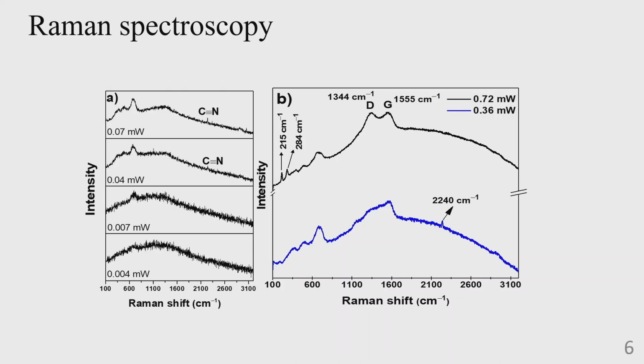Well, now the Raman spectroscopy. We show here the Raman spectrum of the maghemite functionalized with polymer PAN sample, which was studied with different laser powers, as can be seen from this figure. The corresponding Raman modes are not visible in the spectra with low laser powers, due to the low signal to noise ratio. The broad signal screens the optical Raman modes, which is characteristic fluorescence interference due to the organic polymer.